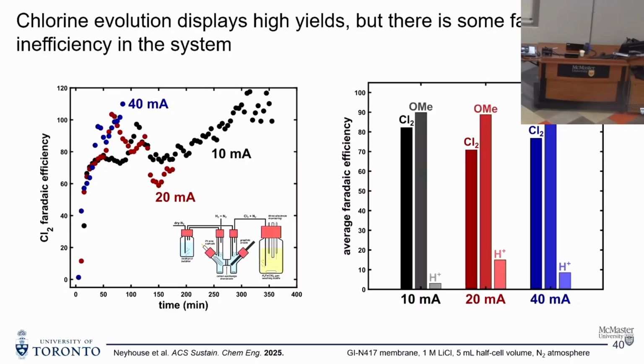And where this lost current comes from, at least as far as we've studied, is methanol oxidation. What happens is you oxidize methanol to something like formaldehyde, and that would liberate acid. So that's where we get this H+. There's going to be more H+ than what we measure, because some of that H+ is going to cross the membrane and neutralize that methoxide. So that's also why we have a lower methoxide yield. But if you take this H+ and stack it on top of the chlorine, your yields of both of those are about the same. So that tells us that's where our Faradaic efficiency is being lost.